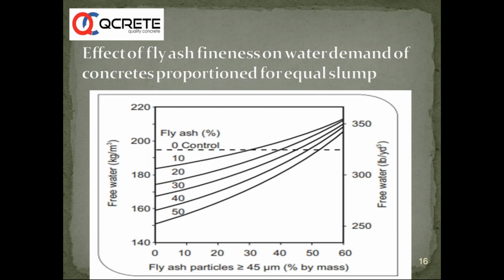This is one of the pictures which shows that as we are reducing the OPC content, as we are replacing OPC content with a certain amount of fly ash, the water content goes on reducing. Typically, if you are replacing about 25% of OPC by fly ash in a mix, you can get a water reduction of about 8 to 10%.